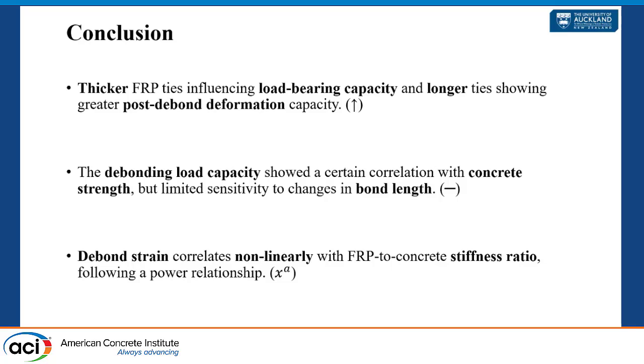And the second aspect is at the material level. We only saw a certain correlation of the concrete with debonding strength, and similarly, a bounded effect from the bonding length. And the third aspect is our proposed model. The debond strain and the ratio of stiffness of FRP and concrete have a nonlinear power relationship. And after we compared actual data with our predicted data, it shows relatively good agreement.